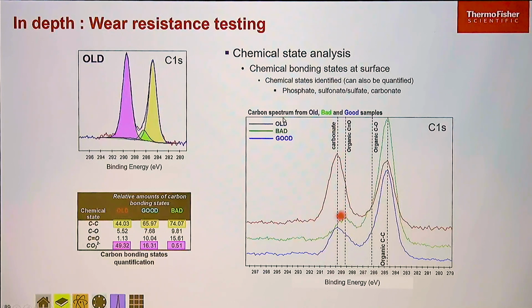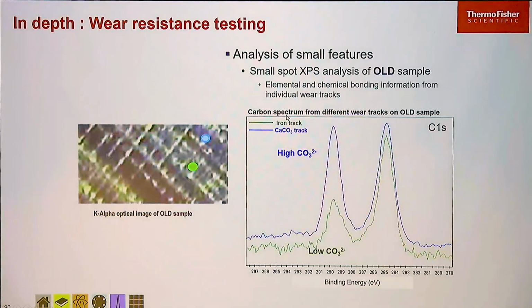And actually in the bad sample, it's not really carbonate, it's more like an ester type functionality. So we can see those differences there and understand that this carbonate should be present at the surface, and in the bad sample, the one where we're seeing wear, we're not forming that surface.